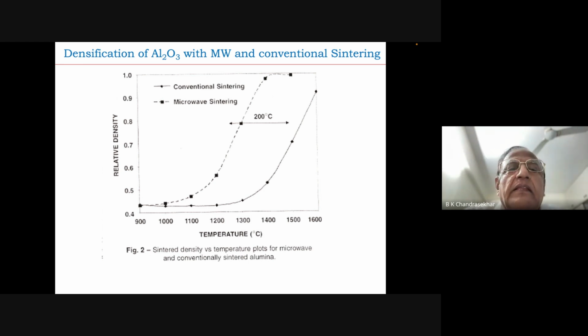Then when you start heating it, first the water goes, and then the binders go at about 400 degrees centigrade - all the CMC, PVA and those things are gone. And then when you continue further, as I mentioned earlier, at about 1200 degrees centigrade onwards, as you increase it, the diffusion of aluminum oxide takes place, and the particles of aluminum oxide tend to coalesce with each other.